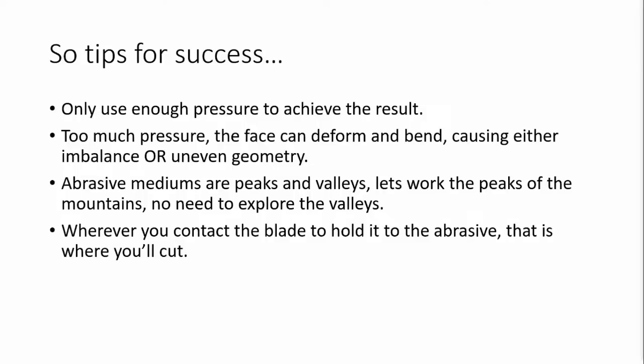If you're pressing too hard, and you can do it with some of the hardest and most difficult to work with carbide steels, CPM steels, you name it, nano powdered steel, you can deform an edge with pressure. I've seen it. You can do it. If you're pressing too hard, you are causing that edge to bend, and now you're chasing the apex, which is when people start to raise up on the stone or abrasive, and they're like, oh, I'm not getting a burr, I'm not getting a burr. Well, chances are that edge is deflecting and bending away from the abrasive, so you're not even contacting the space leading up to the apex.